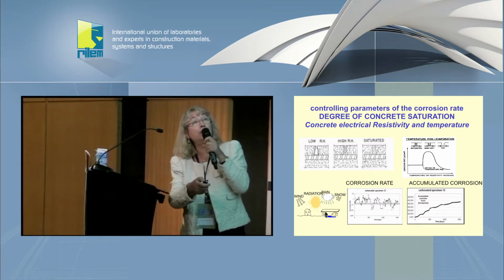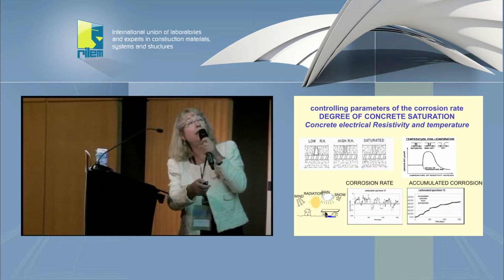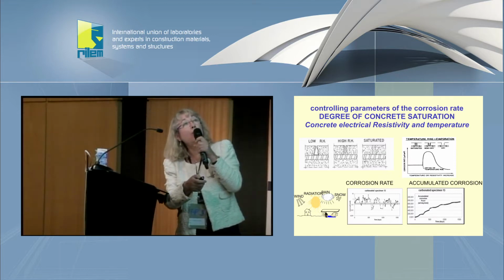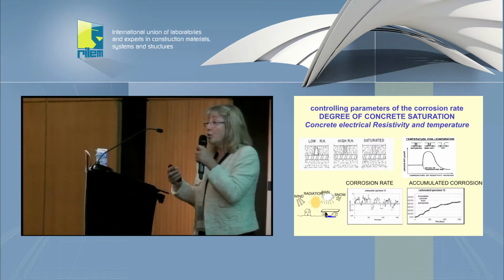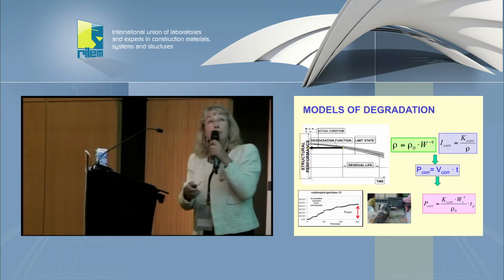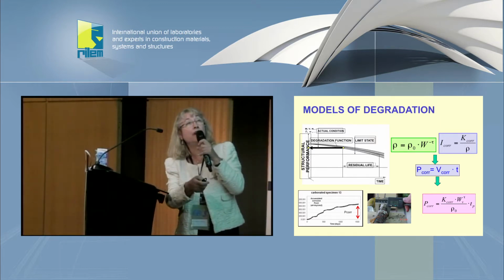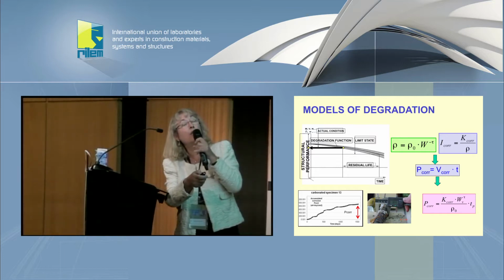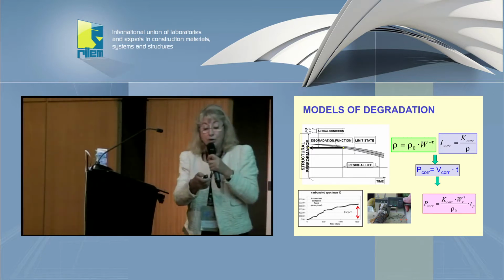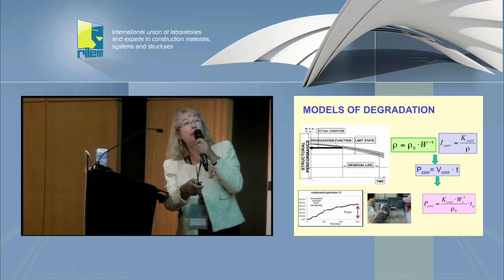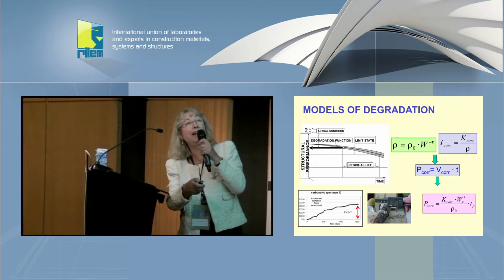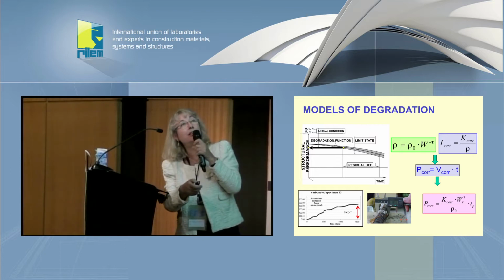Here I would like to illustrate the effect of temperature that I was just mentioning yesterday. In concrete, when the temperature rises, the water inside evaporates. This is a type of curve that I took from atmospheric corrosion. It happens exactly the same as when you have steel in the open atmosphere. At the beginning, as it is wet, you have a layer of water on the steel, and the corrosion rate increases. But as soon as the water evaporates due to the rise of the temperature, the corrosion rate decreases. And this is why it's complex to introduce the effect of temperature in the corrosion rate, because it has an opposite effect depending on the length of time and the increase in temperature. That is conceptual. Finally, if it is dry, there is no corrosion.